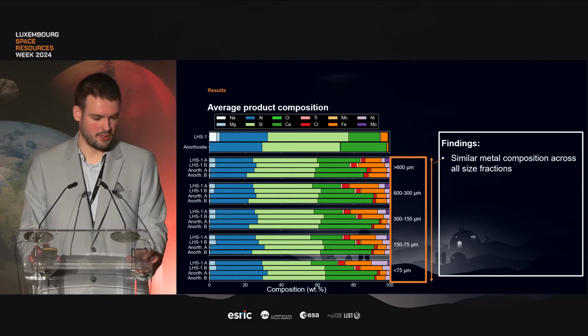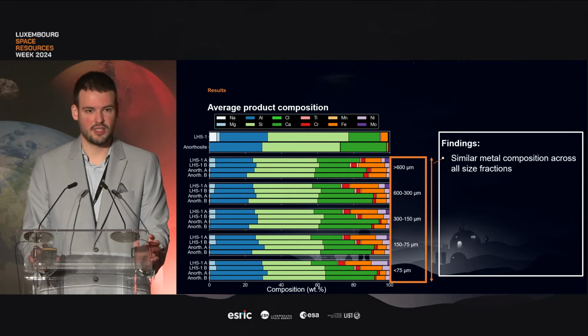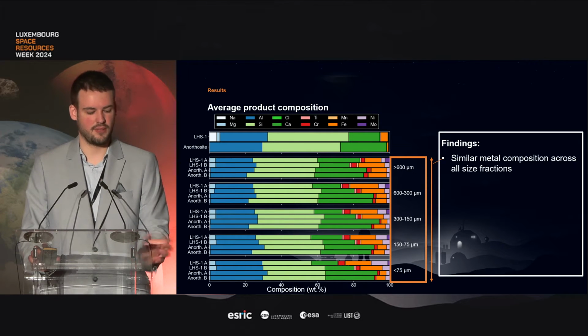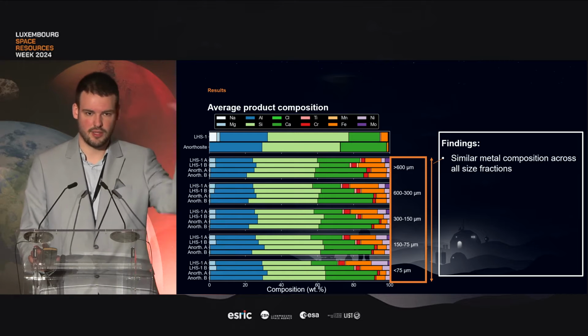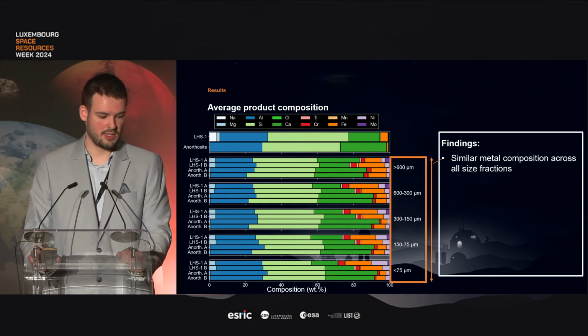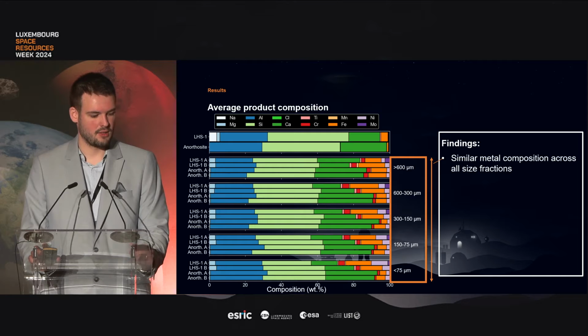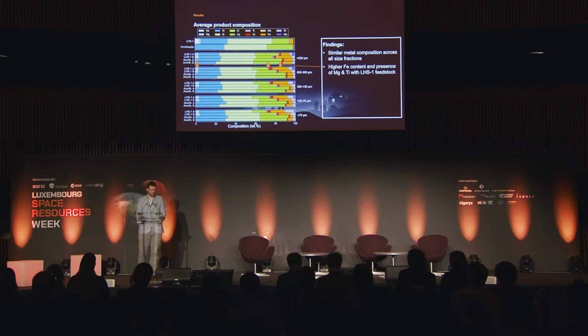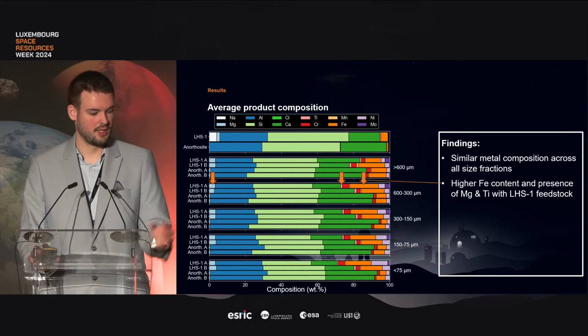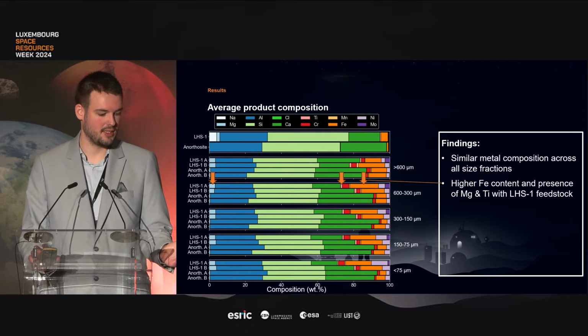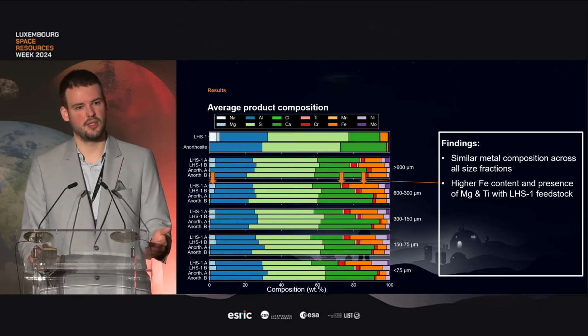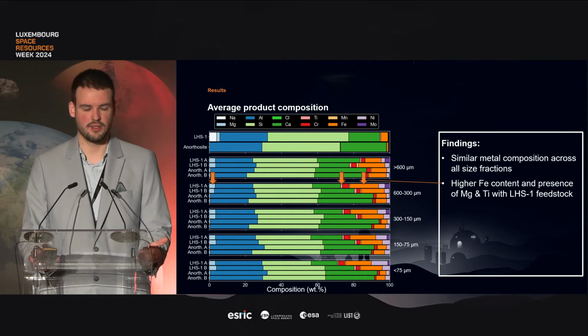Then when we look at it from afar, first of all, we can see that if we move down across the size fractions, the composition is actually quite similar, or at least the variation between experiments is sometimes greater than the variation across size fractions. So the sieving of those products does not seem to be a really useful approach, at least to enrich the material in a specific element. Next, regarding the iron content, as expected, we have higher iron, magnesium, and titanium with the LHS1 feedstock, because in the isolated anorthosite, those elements are not present.